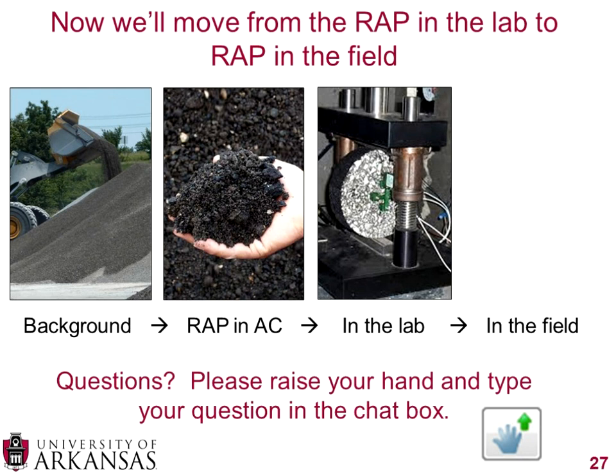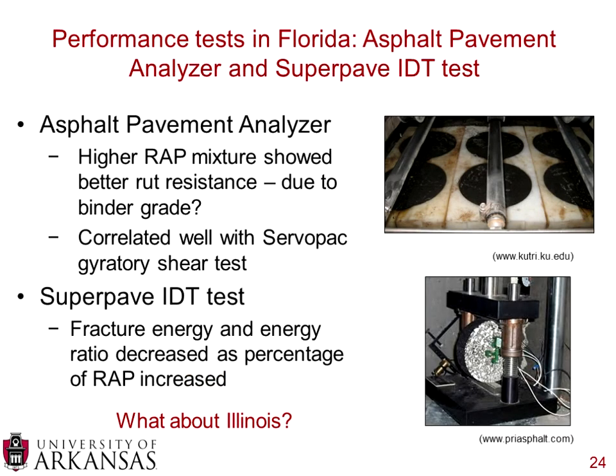Now the second question is, if we use softer binders in the high wrap percentage, how will we address rutting problems? Or should there be other means of control? And I think this is something that Florida touched on. I mentioned a couple slides ago that the higher wrap mixture showed better rut resistance. And yes, they were using a softer binder grade, but did that rut resistance correlate with the high wrap content, or did it correlate with the actual binder grade?